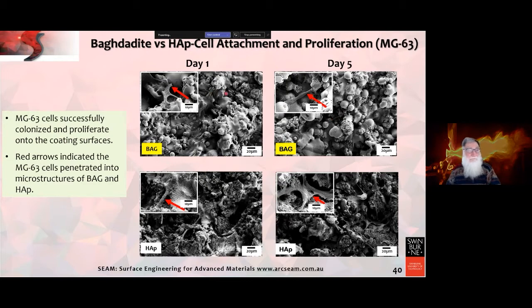We look at how cells interact on baghdadite versus hydroxyapatite. And we're able to see that the red arrows indicate that these cells penetrated into the microstructures of baghdadite and hydroxyapatite, so they are both functional. From that perspective, they allow cells to grow. So the topography is good.